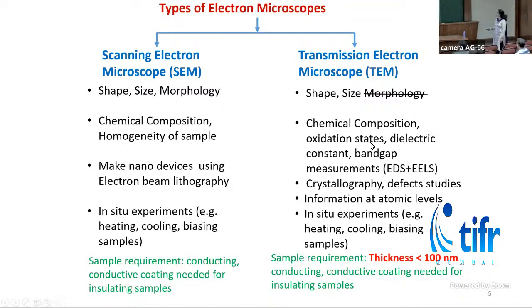TEMs are majorly used to study the crystallography of the sample. We can study the defects in the sample using TEM, and all this information we can get at atomic levels. Here also, if we have heating, cooling holders, we can do some in situ experiments which can give us real-time dynamics of the sample. The most stringent requirement for TEM is the sample. The TEM sample must be electron transparent. That is, the thickness of the sample should be less than 100 nanometers. Here also, the sample should be conducting. If it is not, then some conductive coating is needed on the sample.